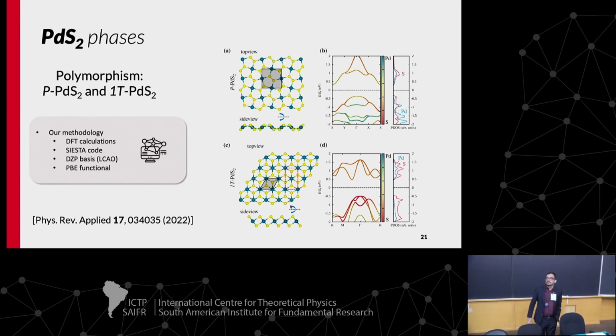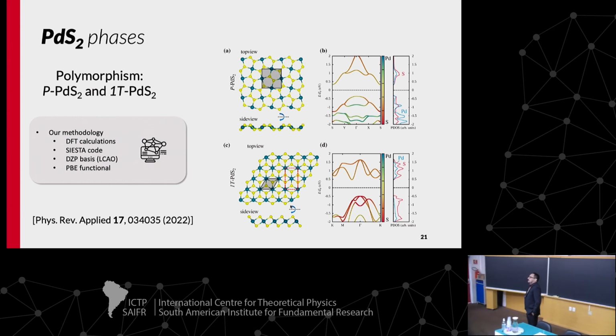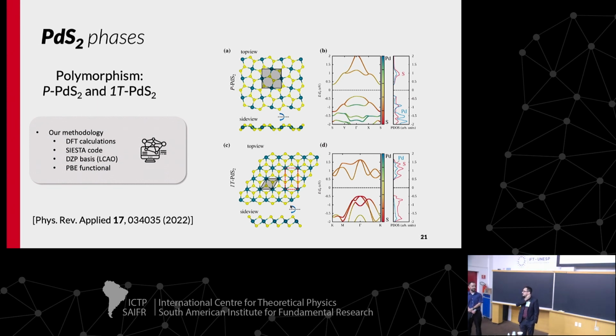Thank you for the talk. Did you use some gap correction method, or how would it affect your results? No, all the band gaps calculated are with PBE in this case, but for this material it's not so bad. When you compare the PBE band gap with the experimental band gap, it's very similar. We can do calculations with hybrid functionals, but maybe we would have a correction of 0.1, 0.2 eV. We can calculate that for the pristine material, but for defects in the supercell it's a very expensive calculation, so we prefer to study only at the PBE level here.